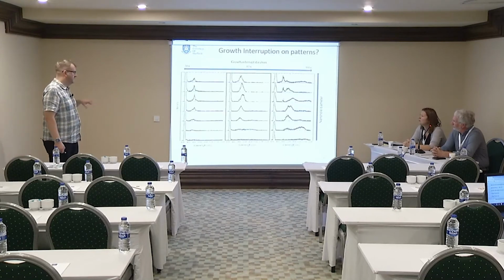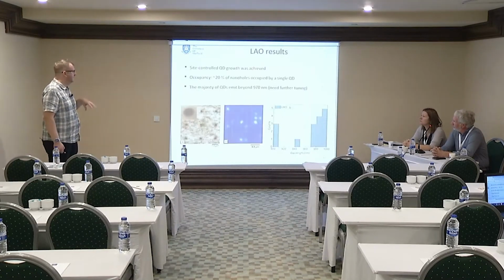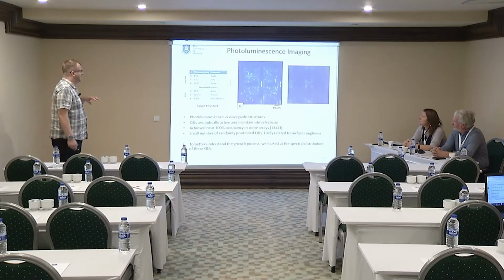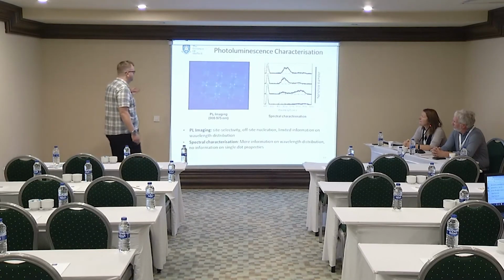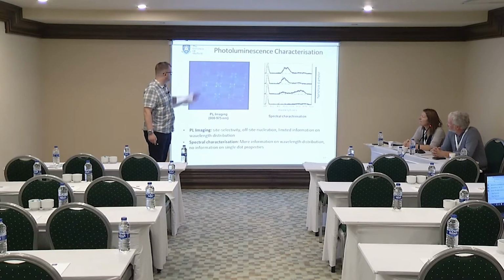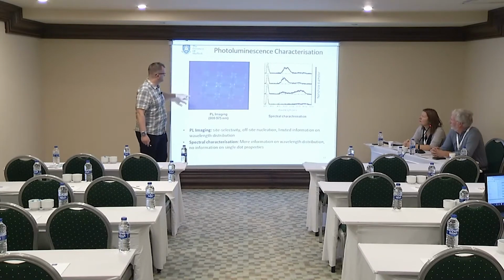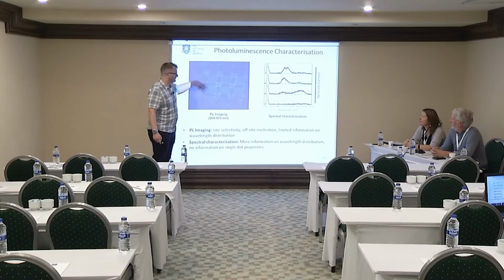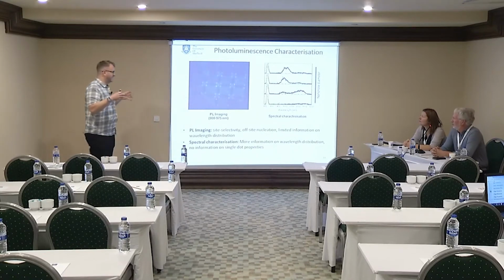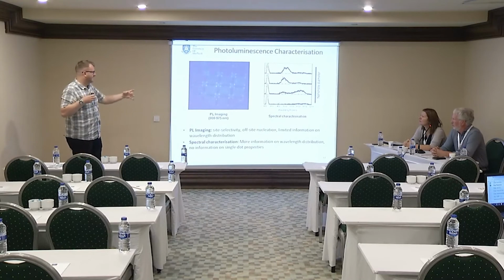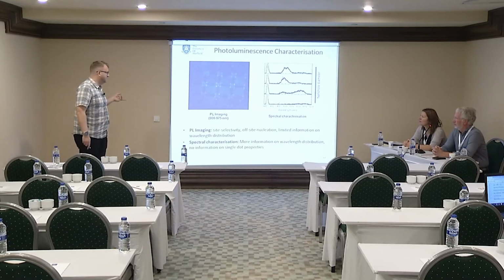So in that sense, we have a reasonable number of patterns on the wafer, but we haven't looked as extensively. The weirdest things we've seen are differences even with just a single array about whether you do or don't have an array next to it. You get quite high occupancy near some of the alignment marks, and if they're too close, you're sucking the dots away. So we saw some patterns where you might be missing one of them, and then everything looks different. So you really have to think about the stuff you're putting around the array. It needs to be close enough to be able to align to make these structures, but if it's too close, it's actually sucking up too much of the indium.